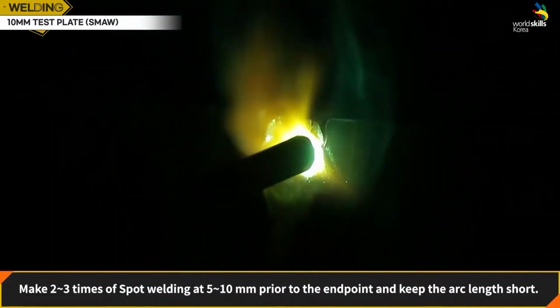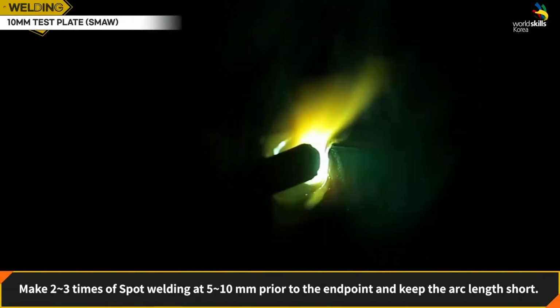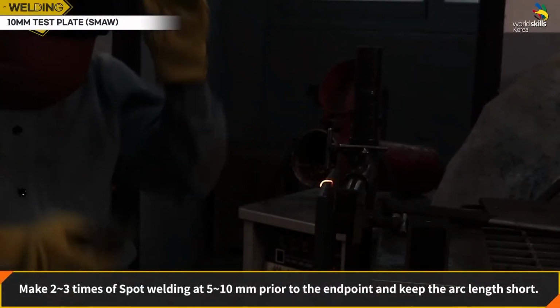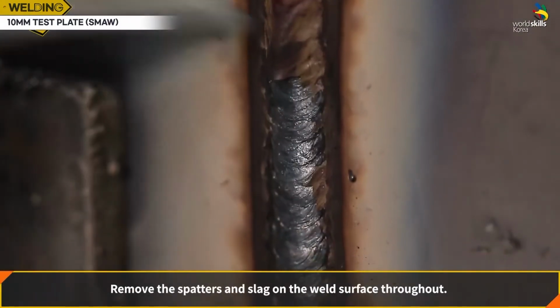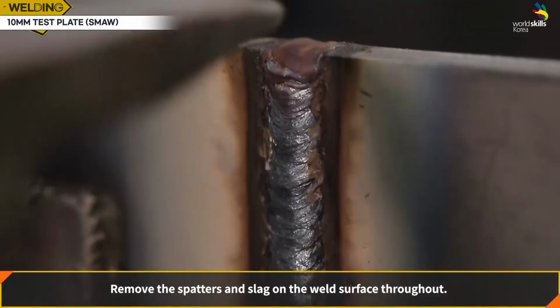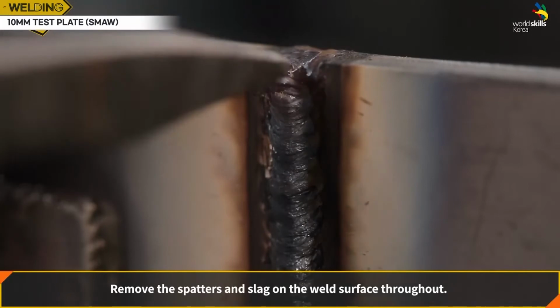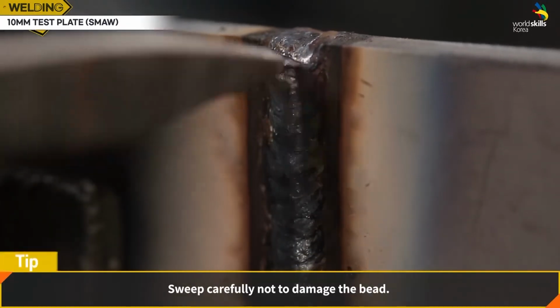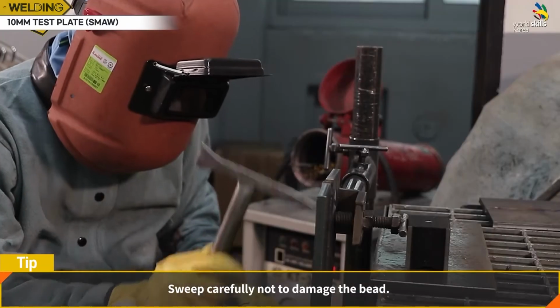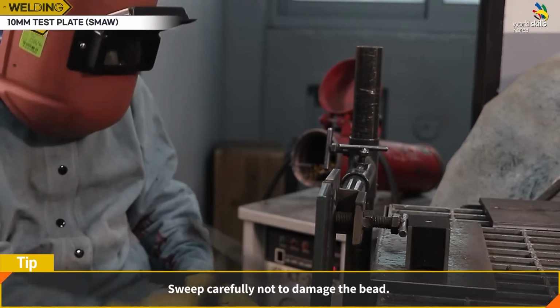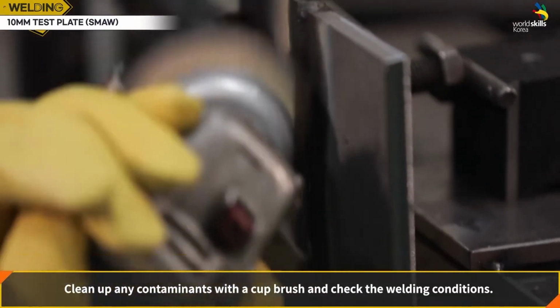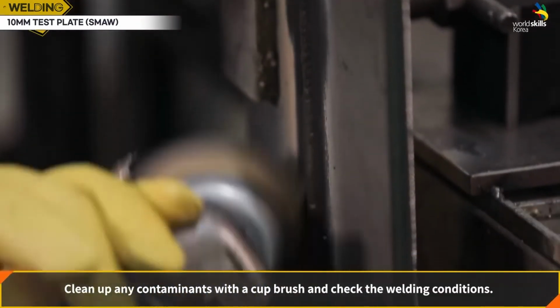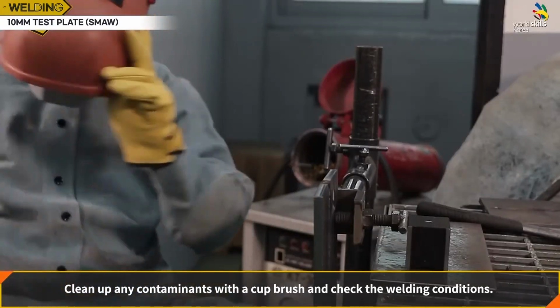Make 2 to 3 spot welds at 5 to 10 millimeters prior to the end point, and keep the arc length short. Remove the spatters and slag on the weld surface throughout. Sweep carefully not to damage the bead. Clean up any contaminants with a cup brush and check the welding conditions.